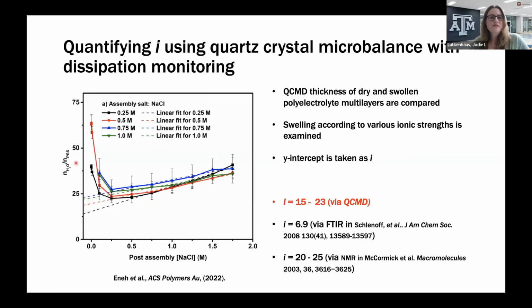So the method he used is a little challenging overall. So we chose to try to develop a parallel method using quartz crystal microbalance with dissipation monitoring. And it's just a method that can measure the swelling of the film. And we can plot the data in the same form that he had. And we also get a linear regime where these polyelectrolyte multilayers assembled in different salts, and later exposed to different salts, have a linear doping regime as well. So we fit the slope and the y-intercept.